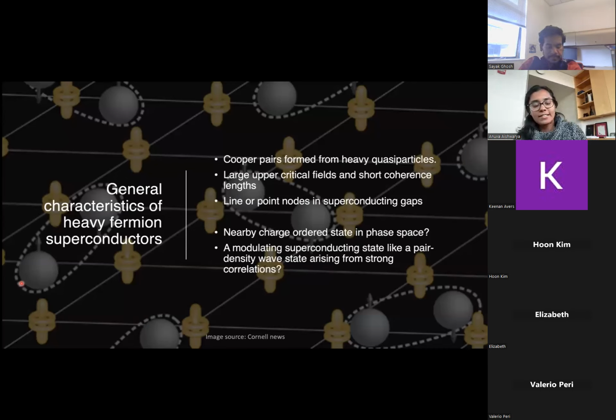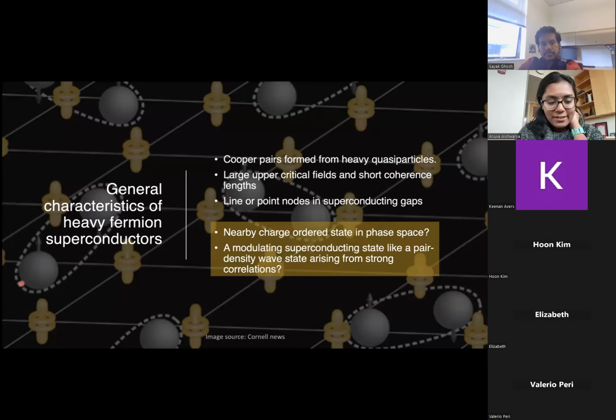Okay, so to briefly recap, some general characteristics of heavy fermion superconductors are that the Cooper pairs are formed from heavy quasiparticles. They exhibit large upper critical fields and short coherence lengths, and there are line or point nodes in the superconducting gaps. All of these have been seen in UTe2. Now, something else is also expected: you can have a nearby charge ordered phase or a modulating superconducting state, like a pair density wave state arising from strong correlations. So can we see a coexisting charge order?